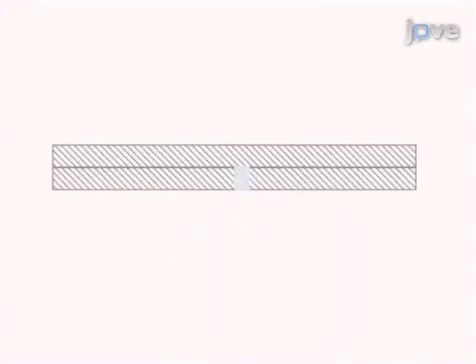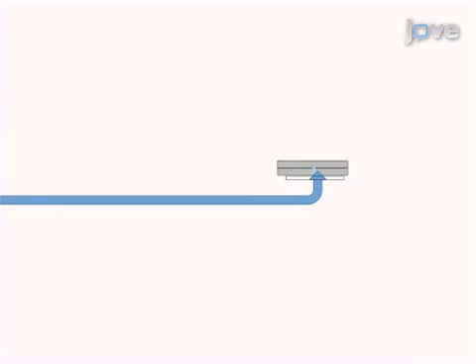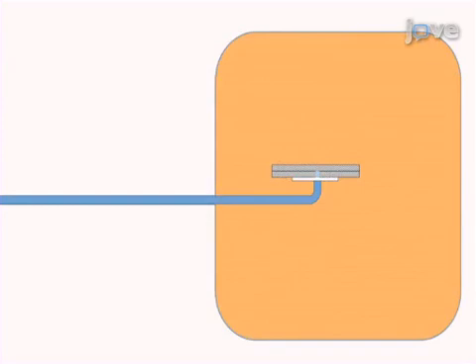The bonded wafers are then placed on a quartz vacuum chuck and the air trapped in the microstructure formed between the bonded wafers is evacuated before the wafers are annealed in a furnace to make the bonding permanent.